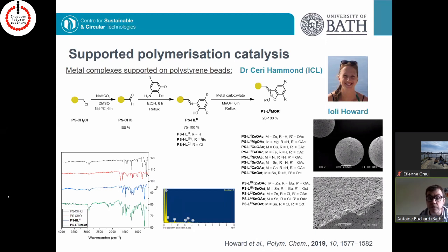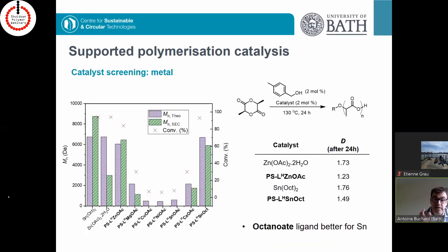clearly had been functionalized. The first step in this project was to do a really wide screening of all these catalysts to see if we had any hits in terms of reactivity. And here you would see that we mainly focus on using what we call melt polymerization. So polymerization where we don't use any solvents, and we do this in the molten monomer, so in molten lactide, at 130 degrees. And we left it for 24 hours.